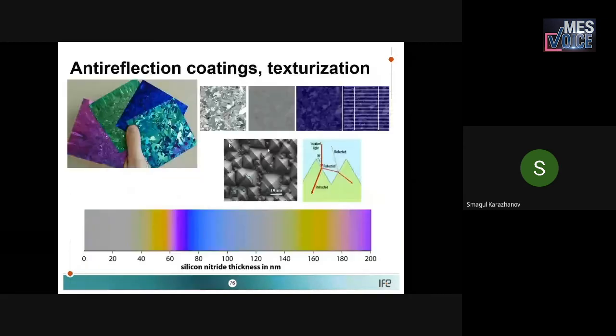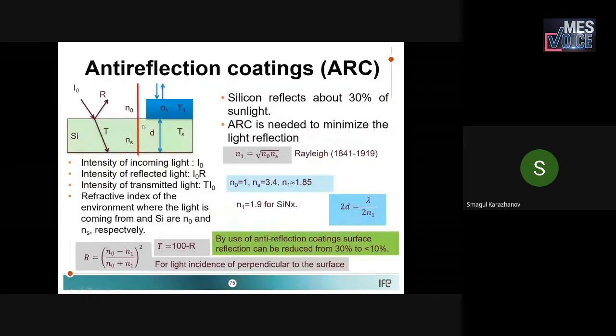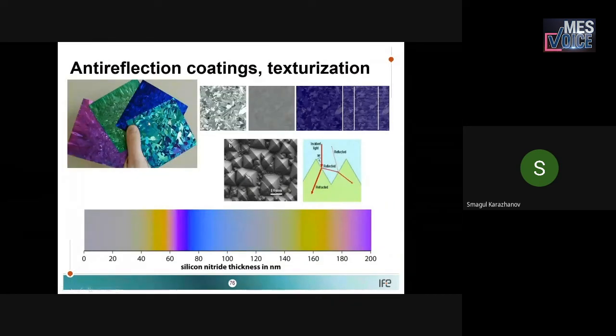And yes, this is a silicon solar cell. I have shown this slide to you before for suppressing light reflection from the silicon surface. By controlling the thickness of this anti-reflection coating, one can control the color of silicon also. The best efficiency is provided when the color of silicon is blue. And this can be done at about 80-100 nanometer thickness of anti-reflection coating. If it is reduced to a little smaller value, then of course one can get green or pink. A different color is possible to get. Just then efficiency will be lower than blue color.